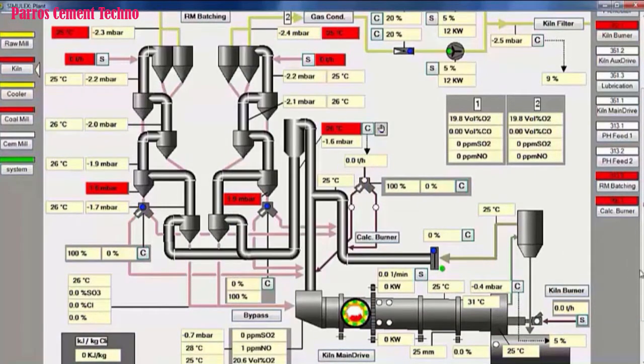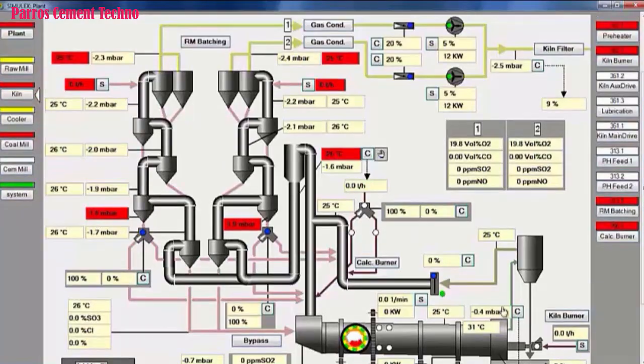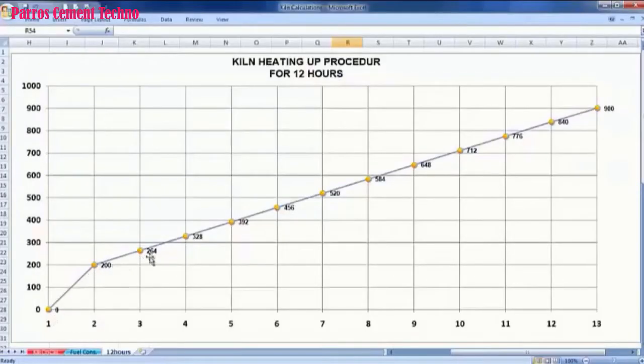Previously we have prepared a heating up procedure curve, and this is an example of heating up for 12 hours. The guide for temperature rise is the temperature at the kiln inlet. The requirement for starting the kiln feed is around 900 degrees Celsius, as a guide for raising the temperature in the kiln's sintering zone and in the kiln inlet. This 12-hour heating up procedure is usually used to start the kiln without replacing the refractory brick.